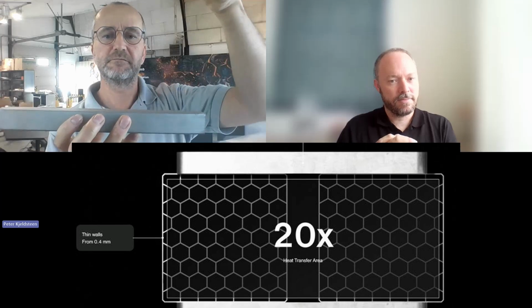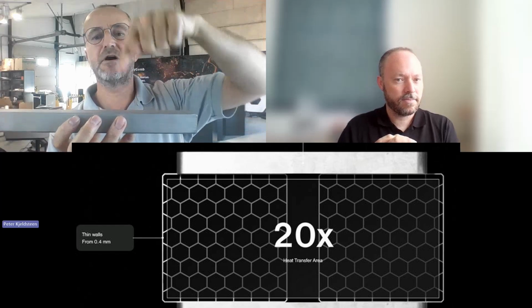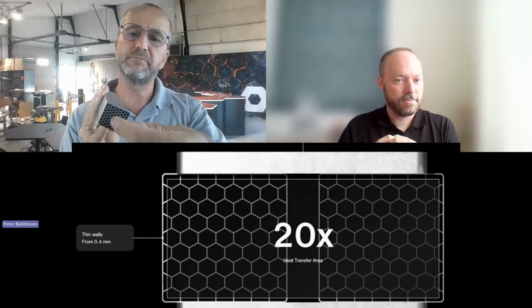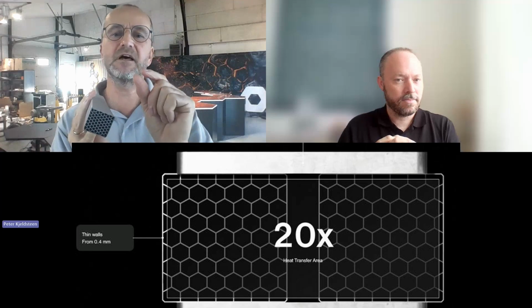and the surface area on the inside is 20 times higher than the outside. It means that just the surface area that is active to transfer heat is 20 times higher. But furthermore, when it comes on the surface, bounce off, it can bounce far away. But inside here, when it hits the wall and bounces off, it hits a wall again just after 3 millimeters, because that's the size of the channels. And that means in a system like this, it will bounce off ding, ding, ding, ding, ding many times. So the heat transfer, the power density of a system like this is up to 60 times higher than we have seen in traditional heating elements.